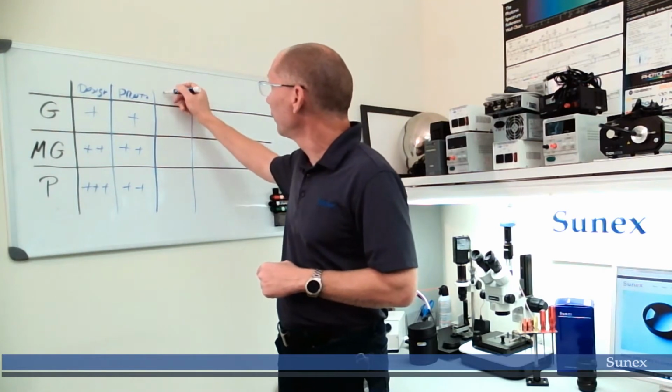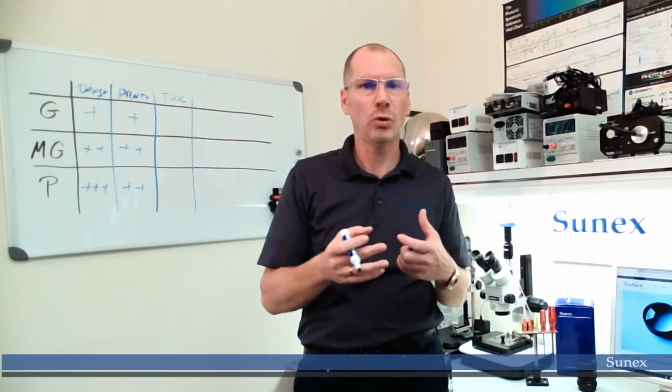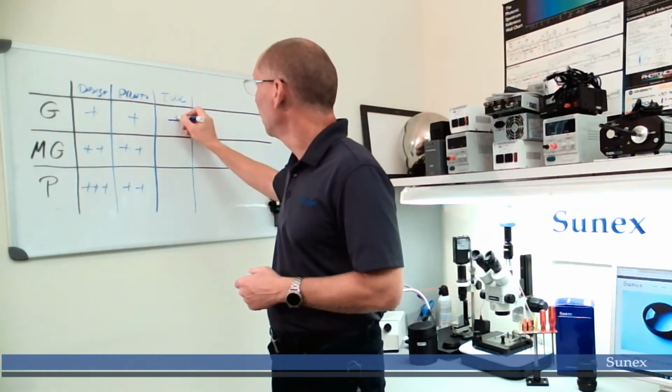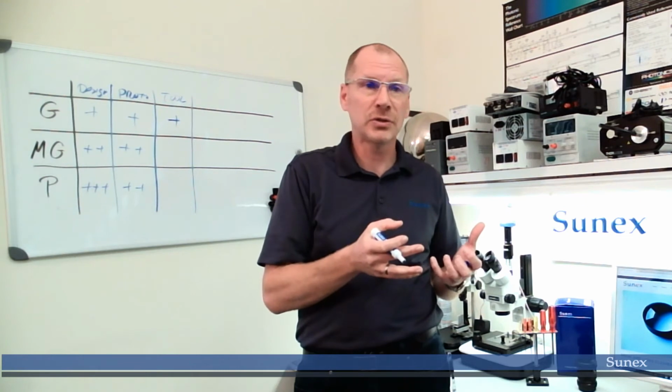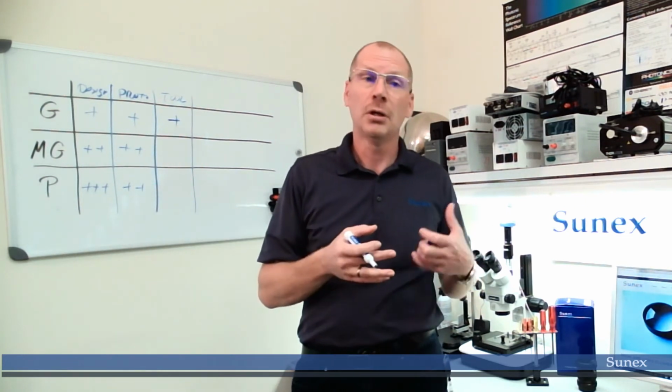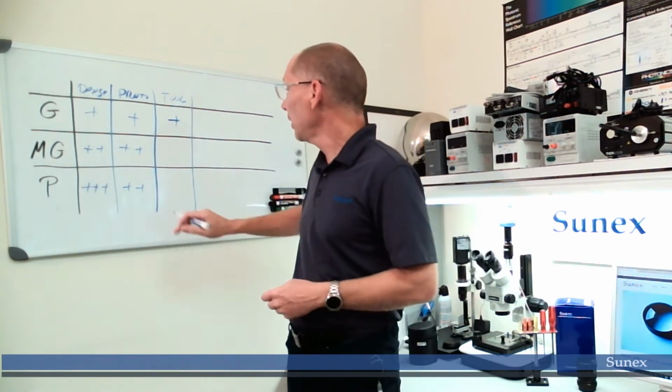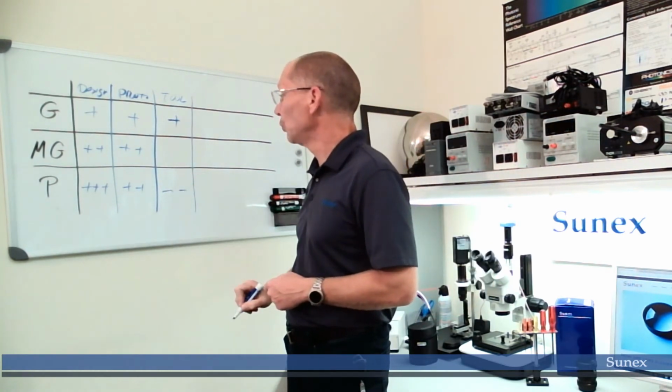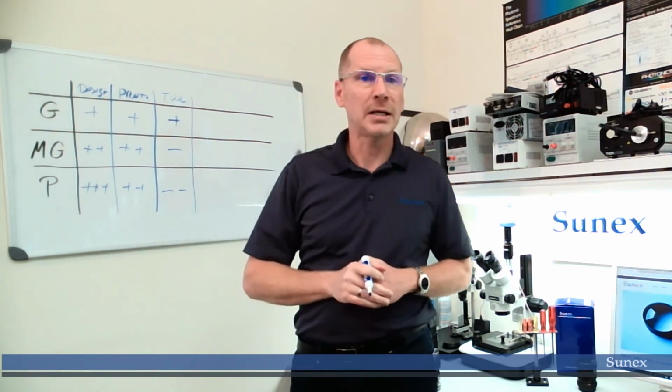If we're moving towards mass production, how about tooling? The traditional glass manufacturing process doesn't require actual tools. It's more like jigs and fixtures to mount the lenses during the manufacturing process or later in the coating process. So again, not too many tools here. Molded glass elements require compression molding systems, and plastic elements require tooling. Depending on the monthly throughput and the overall program lifetime, you will have to decide whether to use 2, 4, 6 or 8 cavities. But there can be some upfront cost when it comes to tooling, and on the molded glass side as well, tooling costs can again vary depending on throughput.